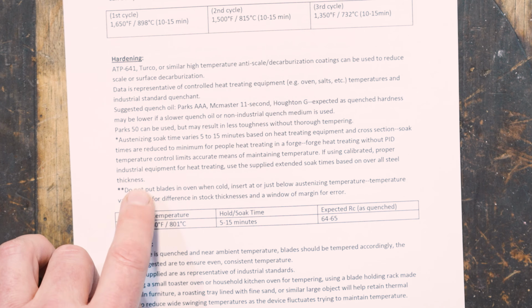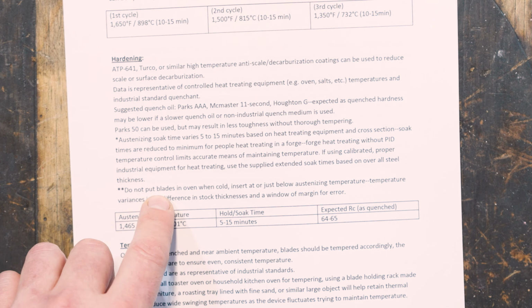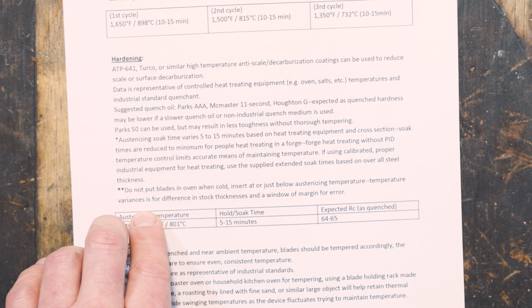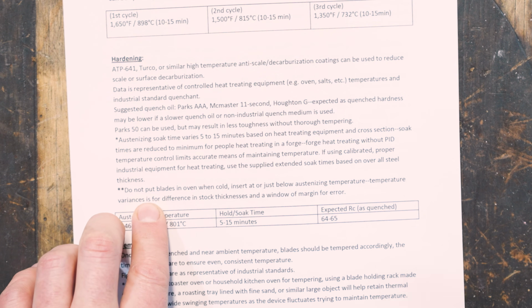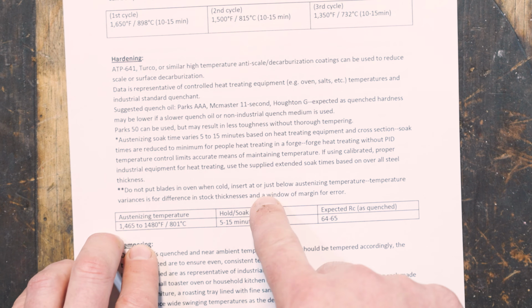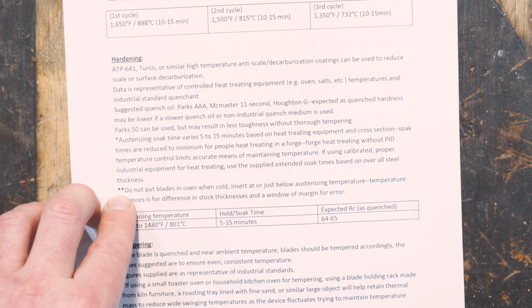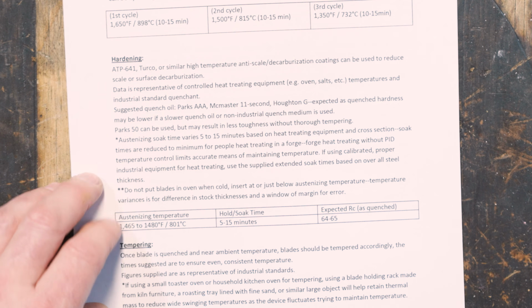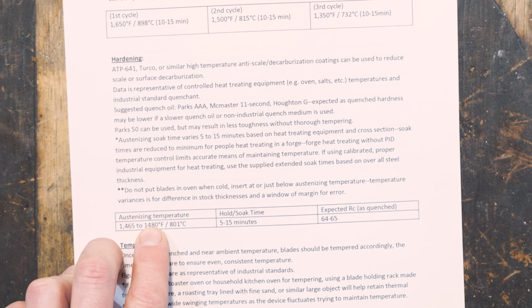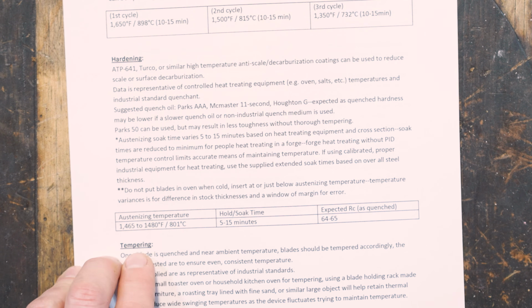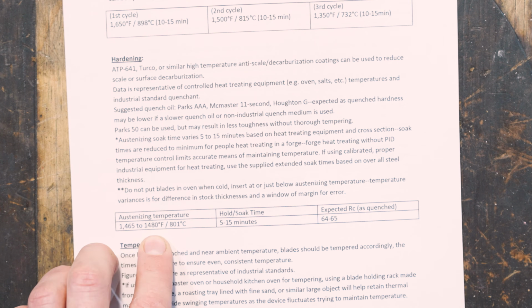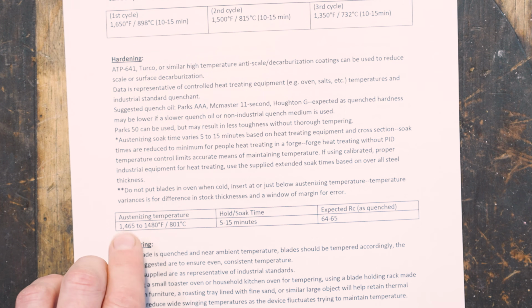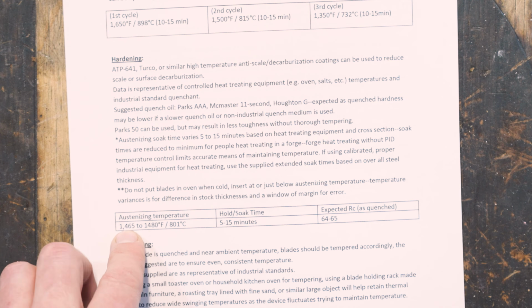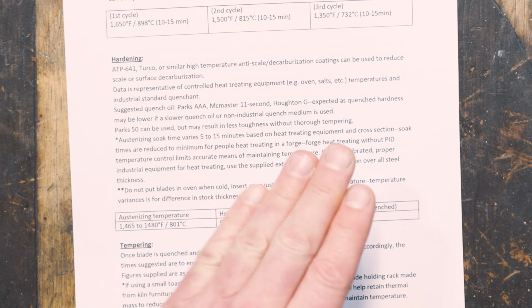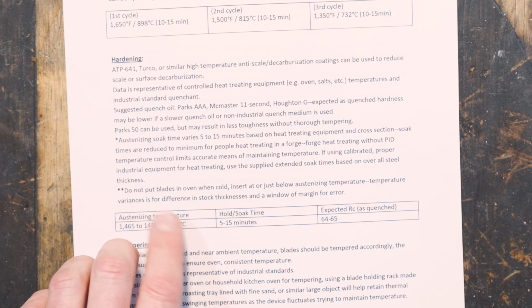And here there's a note that says not to put the blade in your heat treat oven when it's cold. So that means don't put the blade in the oven and then heat it up. Actually get the oven heated up, then put your blade in it. Again, that's another thing that you probably just don't have to do, but it helps with the final result. And then our austenitizing temperature is 1465 to 1480, which I'll probably go in between there somewhere or the high side. I'd always do the low side when I'm trying to get a hamon. That way you're cooling a lot quicker. And then after that, we'll be tempering.